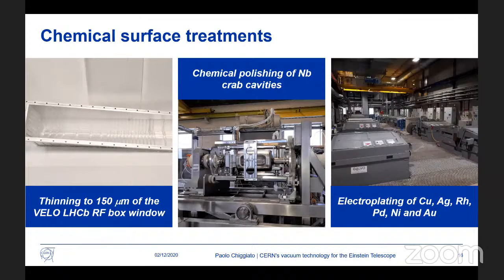Then in the second picture, in the center, you see a bulk niobium cavity, which is called a crab cavity. During the cleaning, we can clean and polish the surface of niobium, and at the same time, we have the possibility of rotation on different axes. This rotation is possible even if inside we have acid like hydrofluoric acid. In the last picture, on your right, you see the facility we have for the electroplating of different metals. Copper, silver, rhodium, palladium, nickel, and gold are the most demanded.